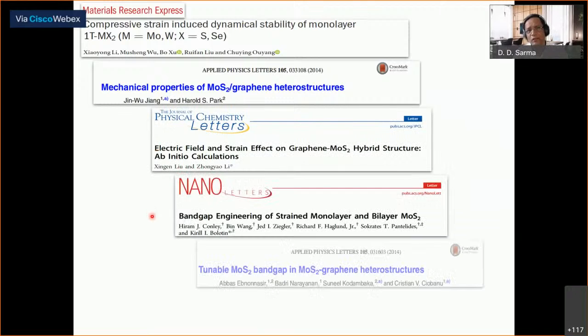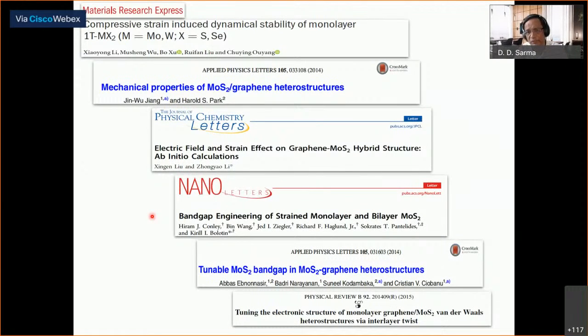As you can see, there is a compressive strain, and this compressive strain may drive the 2H form of MoS2 into one of the T forms that I was mentioning, and that's why I wanted to show you that. And there are many, many claims. We looked at this particular problem, and we also saw that, yes, there is a strain that can be measured by Raman. I'm not going to show you that here, that there is approximately a 1.2% compressive strain on the heterostructure that we looked at.